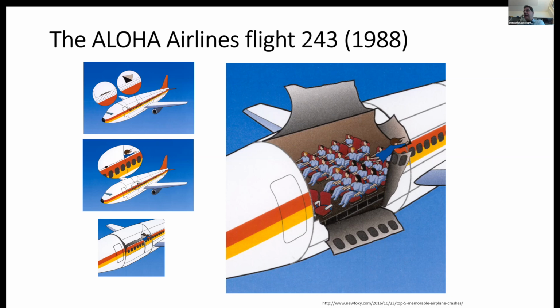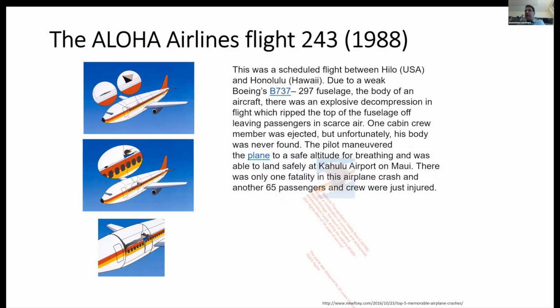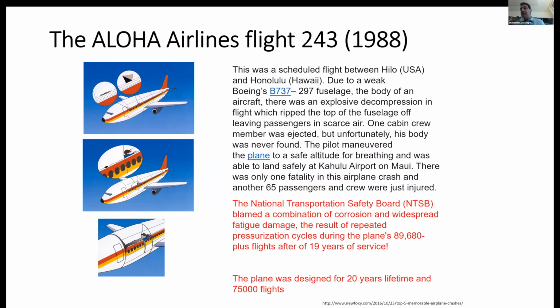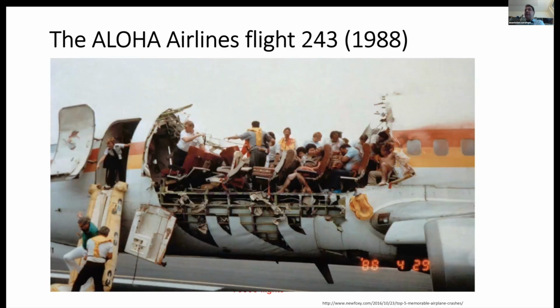And why did it open like that? The investigation showed afterwards, and I have it written here, that the plane was designed for a 20-year lifetime, and it was already 19 years in service, but it was designed for 75,000 flights. And because of the short distance between the two islands, the plane did much more than this. So at the time of the damage, it had done 89,680 cycles. So almost 15,000 more than the design lifetime. And this means that it was pressurized and depressurized 15,000 times more. And that's why it failed. And it ended like that.